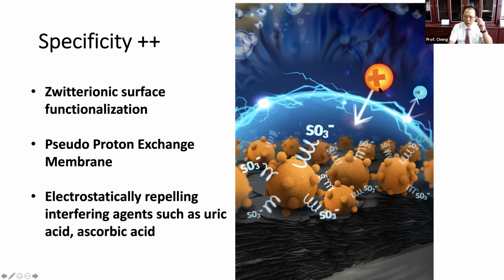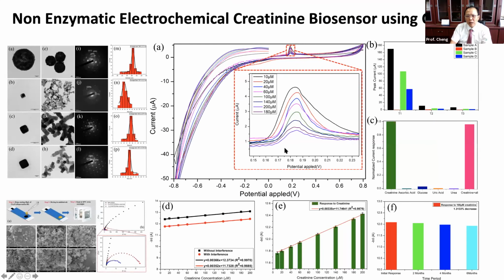So the creatinine is the one. Okay, so we increase the specificity by using this zwitterionic modification technique. Here is our result. So you can see the sensitivity. This is the single crystalline nanoparticle, and at different steps we can have different morphology and different size. After testing, we found sample C is the best. It's a cubic nanocube. And by using this nanocube, we can test onto the sensor.